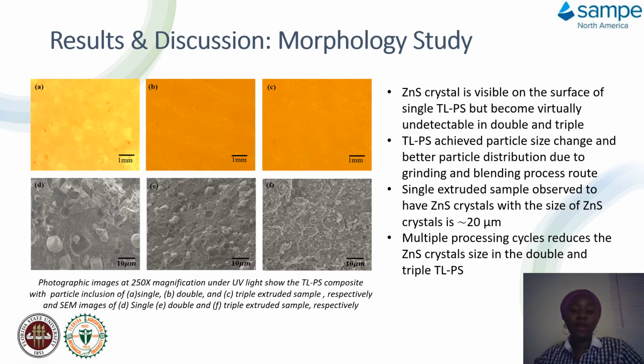So after carrying out these tests, the SEM result and the UV light on the first process show that there's a crystal within the surface of the material in the first process, and when we move on to the second process, the crystal is not as visible as in the first process. Same thing happened on the third process. And when we check with the SEM, it confirms that the size of the crystal is being reduced from one process to another.